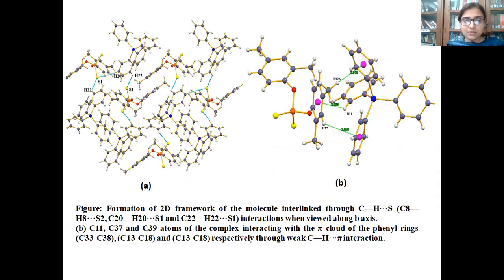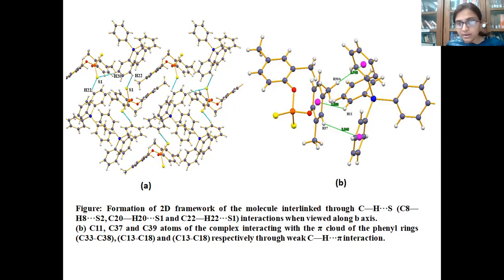This slide represents the C-H···S interaction present in Salt-1. When the various monomer moieties are interlinked through this C-H···S interaction, a network-like structure similar to that in Figure A is formed. Figure B represents the C-H···pi interaction, where the centroid of the phenyl ring interacts with the hydrogen H39A of the anionic moiety. All these interactions result in extension of the molecular structure of the salt, further enhancing the stability of the complexes.